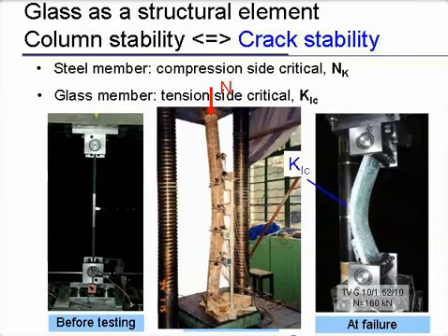And what happens is that when you look at column stability and crack stability, well, for column stability, you have the critical compression, and the compression is critical, so the size where it's going to fail. When you look at glass, guess what? It's the tension which is critical. Of course, now you have a behavior where you have divergence phenomena with second order effects. The more you load, the more you have the thing going out of plane because of imperfection. And at the end, with this secondary bending, at one point you reach the toughness of the material on the tension side, and that's how it's going to break in this case.